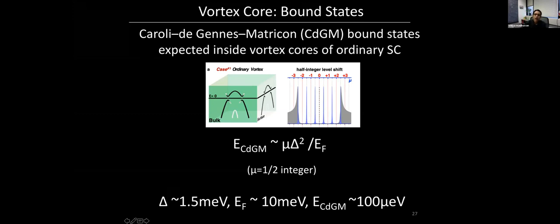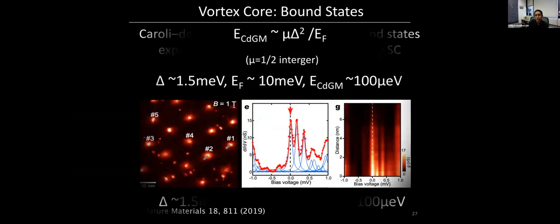And the answer is that the energy of these trivial vortex core states is given by this, where delta is the superconducting gap and this is the Fermi energy. Now, if you think about the surface state that we see in FeSeTe, the Fermi energy is less than 10 millivolts, and the superconducting gap is around 1.5 meV. And if you plug these numbers in, you realize that the trivial bound states should have energy scales of about 100 microvolts, which is actually pretty large for STM at low temperatures.